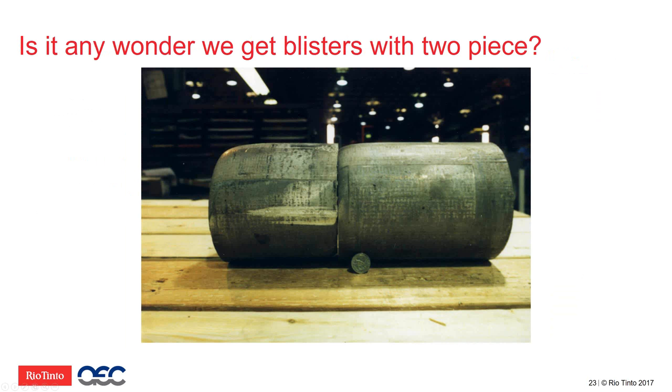Now, by looking at this picture here, I'm sure you see what I'm going to say. This is a two-piece billet that has been sheared. And so two-piece billets naturally are likely to generate air entrapment, especially with a poor log shearing. So two-piece billets are not recommended for any kind of structural application. For anything else, they can be used, but they have to be properly handled.